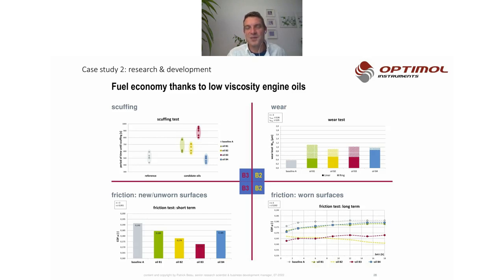And those long-term tests are also made with aged oil, because if you're running a machine in the field, you will end up with worn-out situations on the surfaces, as well as aged oil conditions. As you can see here, the friction is also decreased for all the variants compared to the slightly gray line of reference. And it's very easy to mark the most beneficial candidates. Let's say for scuffing, it's the red one, whereas the situation of the yellow one is the best elsewhere, and so on.